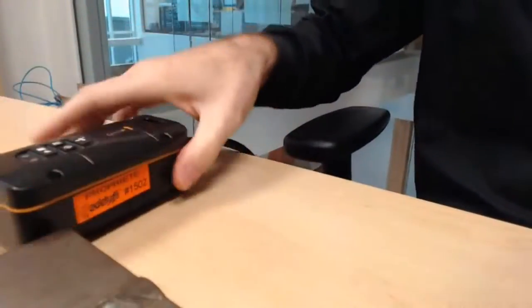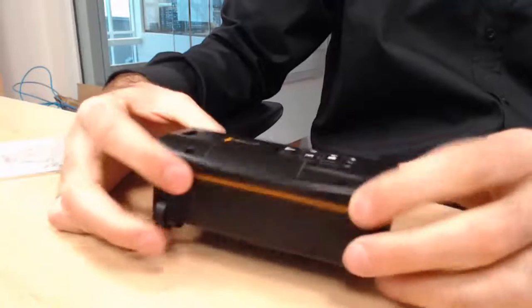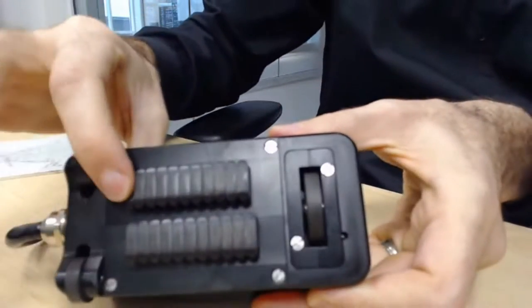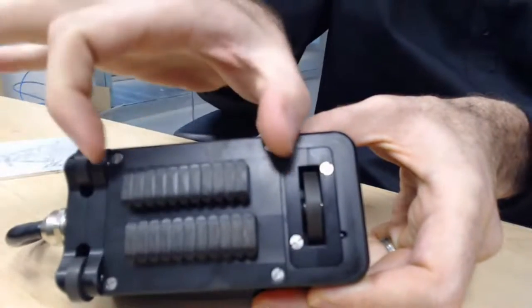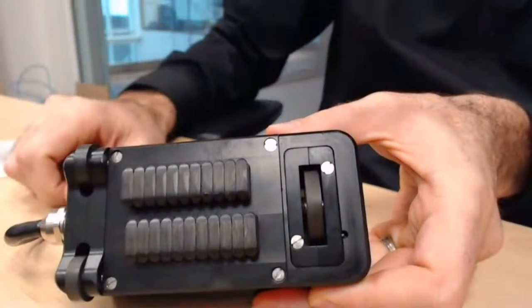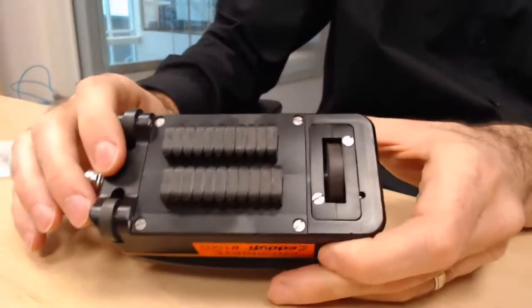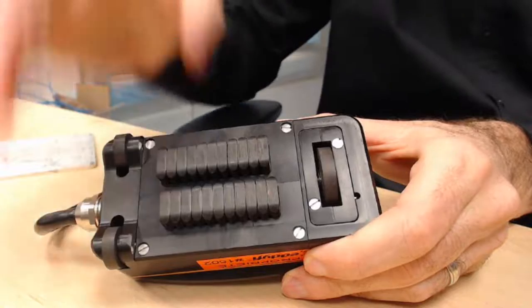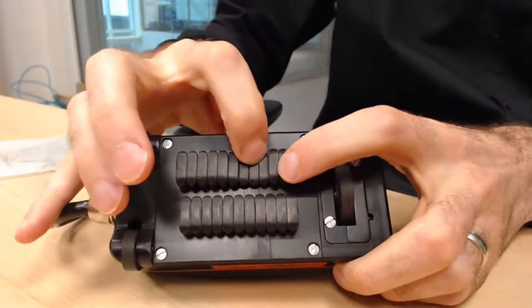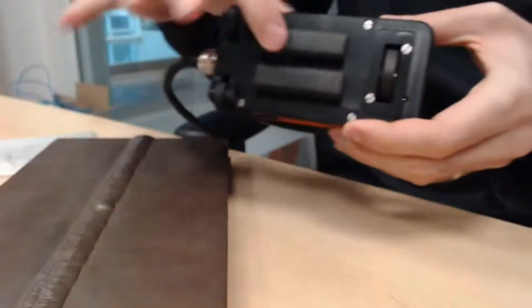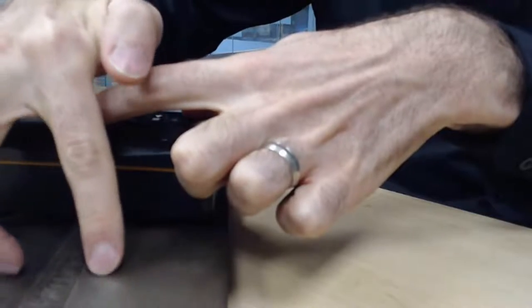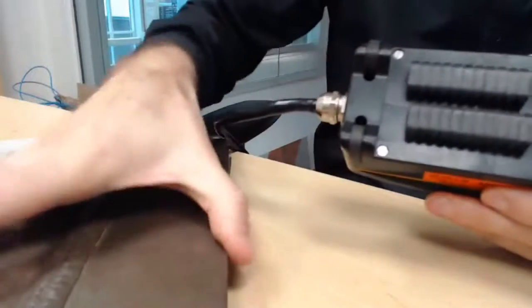This is the Shark probe, the array probe that you have seen for a while now. We call this one the Array probe because it's made of 22 elements individually spring-loaded so that you cover essentially two inches in one pass. You're inspecting two inches wide, about 52 or 53 millimeters. Each of these elements is spring-loaded individually so that if you have a weld, it ensures good contact on the cap, on the toe of each side and on the heat affected zone.